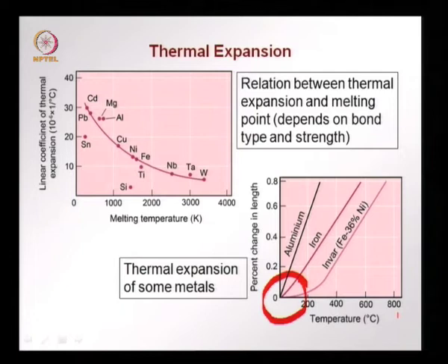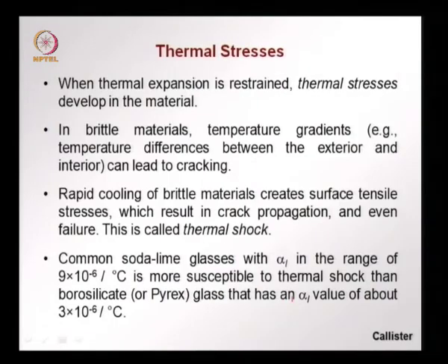From one day to the other we can have a different ambient temperature, but we always want to have the same reference. So, in this case calibration is done with reference to an INVAR bar, which we know that over normal temperatures, even though the temperature is changing, will not change its length. So, that is an application of INVAR, and this is one of the few alloys which do not have any significant thermal expansion over a wide range of temperatures.